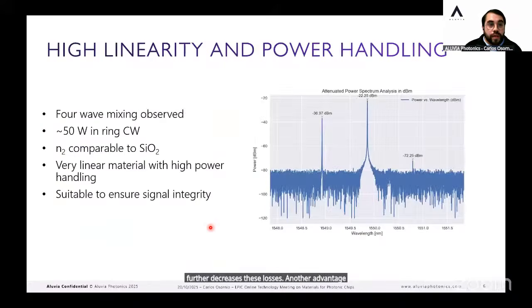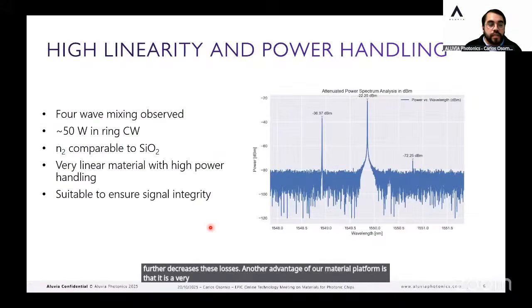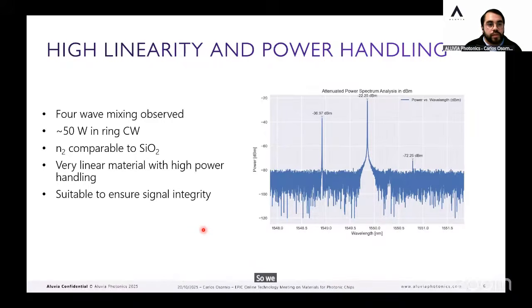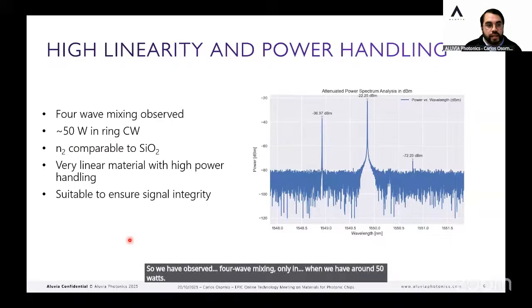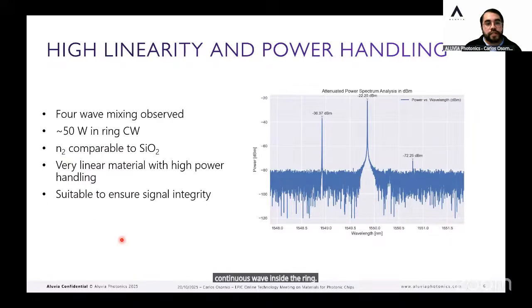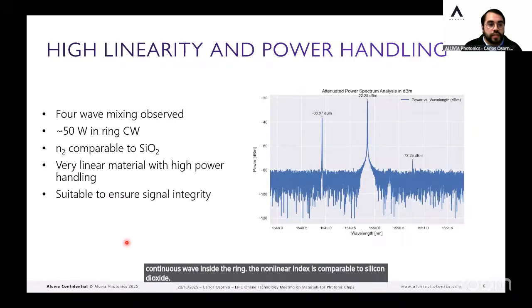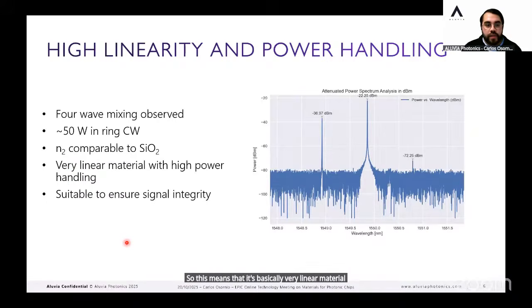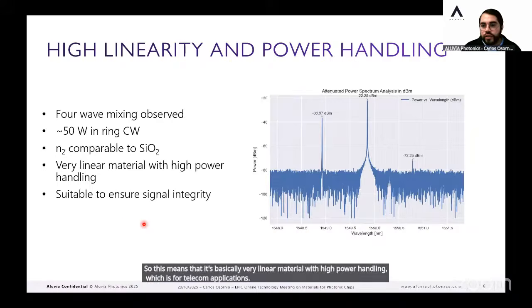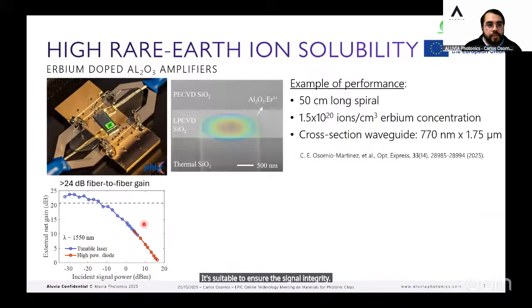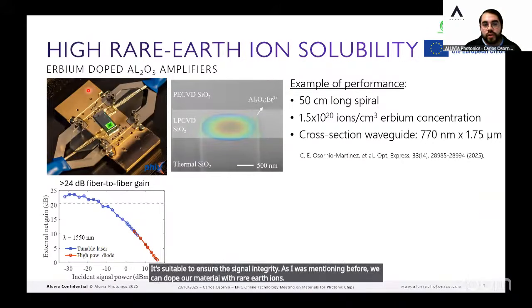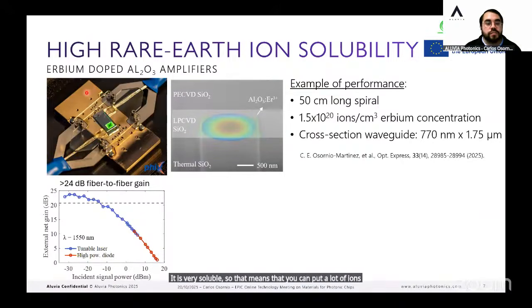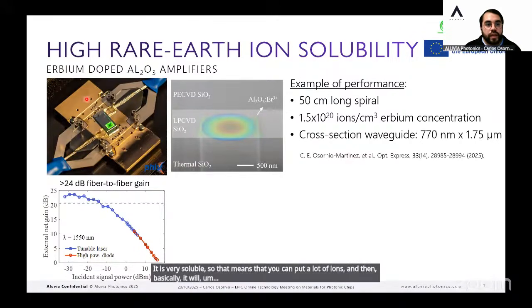Another advantage of our material platform is that it is very linear and handles a lot of power. We have observed four-wave mixing only when we have around 50 watts continuous wave inside the ring. The nonlinear index is comparable to silicon dioxide. This means that it's basically a very linear material with high power handling, which for telecom applications is suitable to ensure signal integrity. As I was mentioning before, we can dope our material with rare earth ions. It is very soluble, so you can put a lot of ions, and they will dissolve well into the matrix.